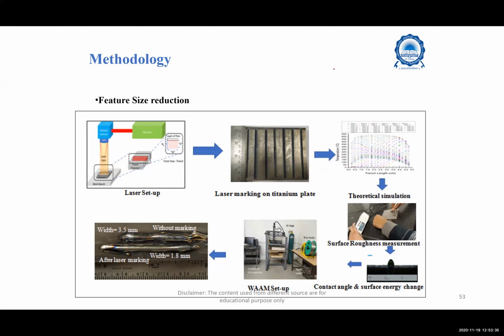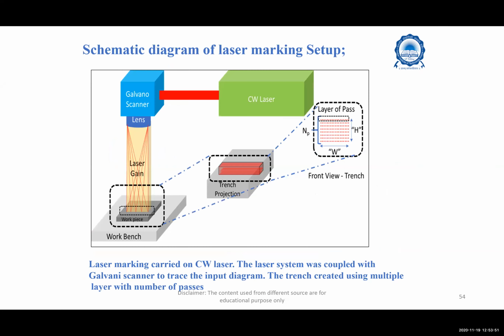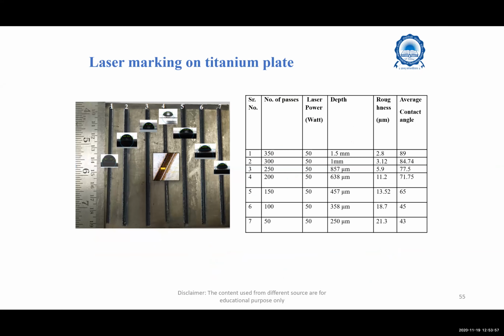In fact, this is an attempt we made in our lab. This is the layer width of around 3.5 mm with the process parameters without marking, and we could achieve a width of around 1.8 mm after marking. So we could even achieve a thin sheet. We went for a complete analysis. First we did a marking, and then we went for a deposition.